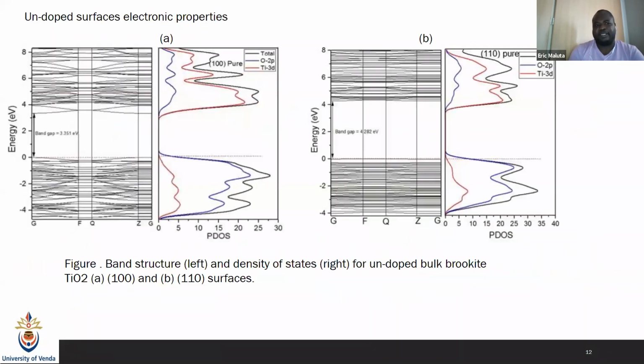And these are the band structure and the DOS. Here we have the pure 100 and 110 surfaces. Then you can see that the surfaces have a higher band gap compared to the bulk structures, which is also in line with the other literature saying the surface has a higher band gap compared to the bulk structure, due to the change in the atomic numbers and atomic structure of the bulk and the surfaces. Because to get the surface, we are cutting the bulk into different surfaces.